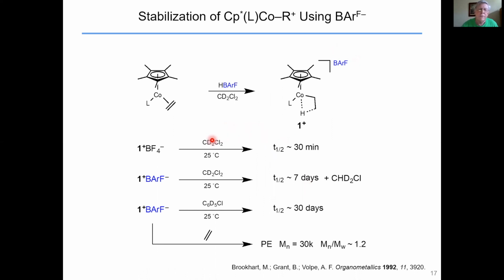And if we now looked at the lifetimes of these species, the BF4 salt had a half-life in methylene chloride of about 30 minutes. If we used the BARF salt in methylene chloride, the half-life was about 7 days. And as it decomposed, we formed chloromethane. We then turned to chlorobenzene. And in chlorobenzene, the BARF salt has a half-life of more than 30 days. So that solved the stability problem. The other advantage of BARF is that the salt is extremely soluble. So we can do very low temperature NMR spectra of these species and really see a lot of detail.